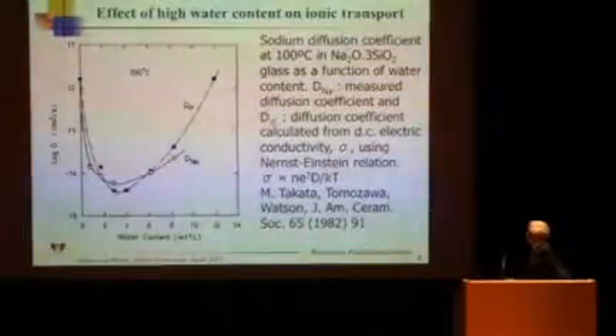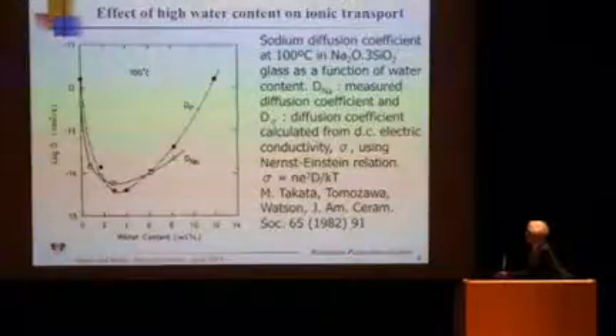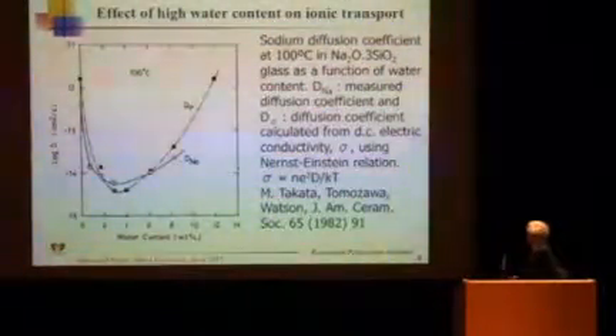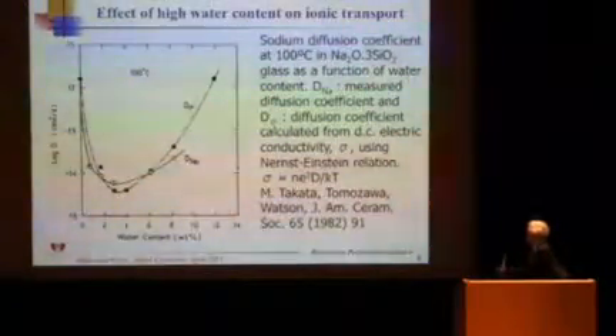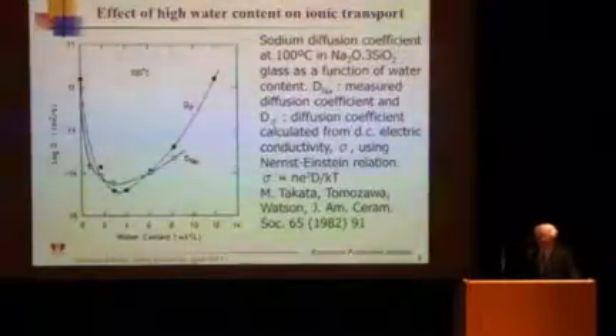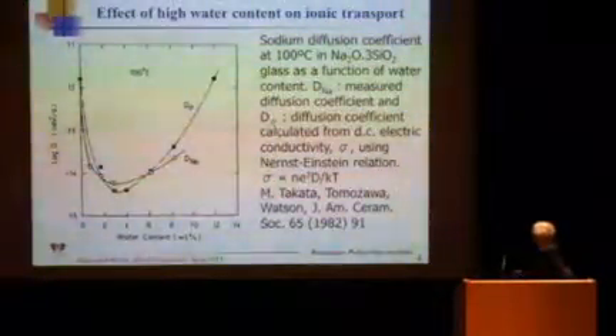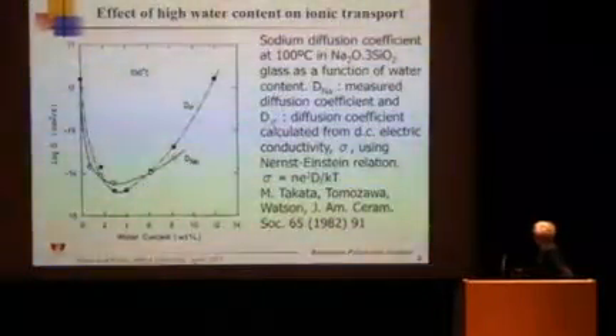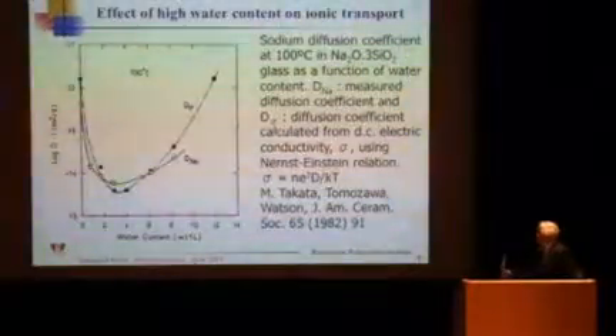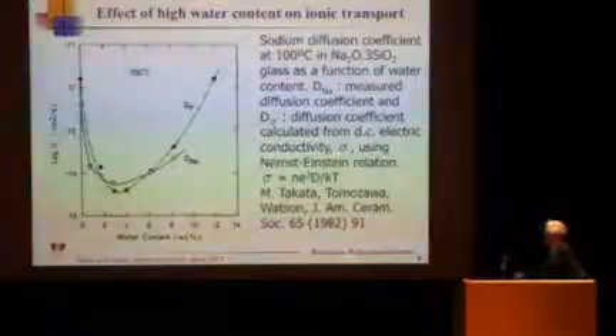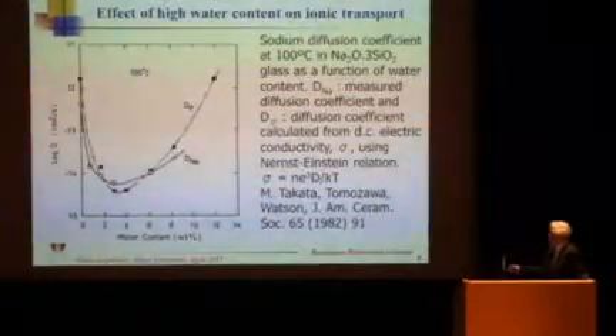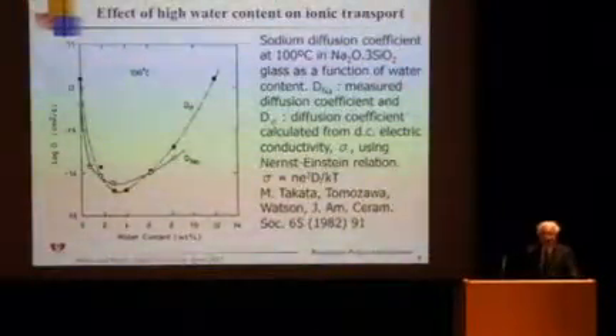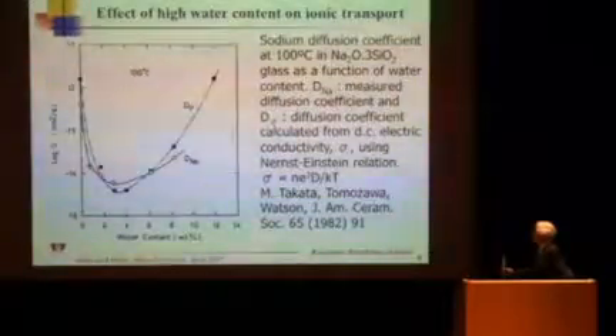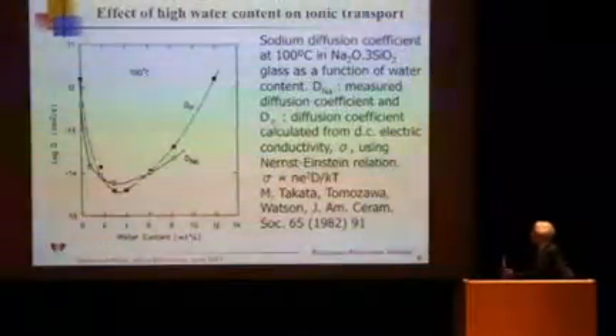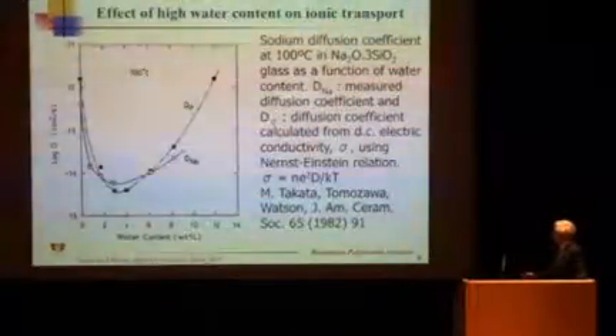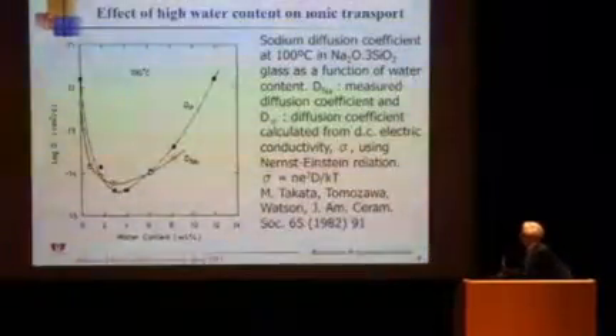This one is the electrical conductivity, the sodium diffusion constant in a similar glass as a function of water content. There are two lines: one is the diffusion coefficient of sodium measured by the isotope tracer method, and the other was by measuring electric conductivity, and knowing how many sodium ions are in it, you can calculate the diffusion constant of the sodium. They seem to agree with each other within experimental error. It shows that a small addition of water dropped the diffusion constant tremendously. Before this work, some people reported the diffusion constant would increase with water content, or decrease with water content. By measuring a large concentration of water effect, we can definitively say this is the trend.